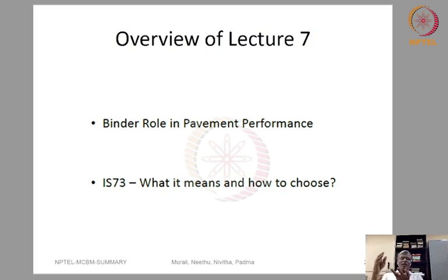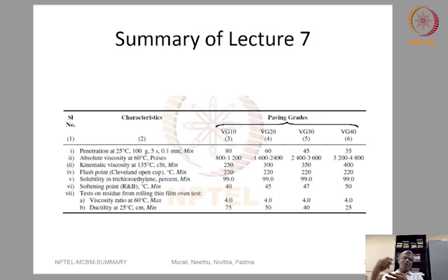Softening point clearly tells you the solid fluid transition, but it is more like a consistency test in addition to penetration. There have been many attempts made to relate penetration as well as softening point to the performance, but not much has actually been achieved.